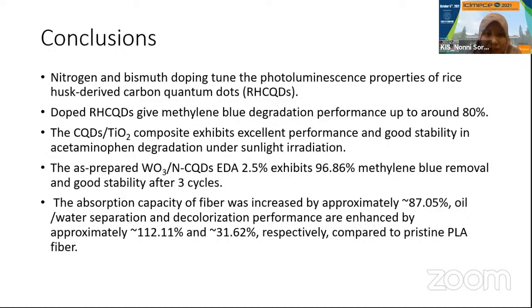And then this material undergoes immobilization, right? So we immobilize it into the fiber, the polylactic acid fiber. So we manage to use it for oil-water separation. We can improve the oil-water separation by around 87% in comparison with just PLA fiber.